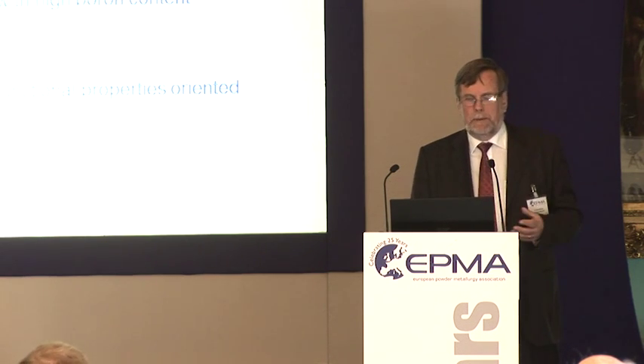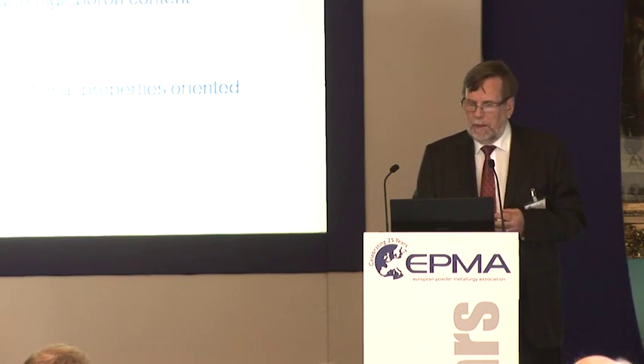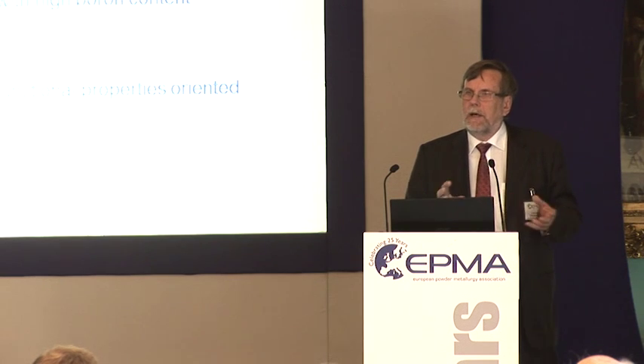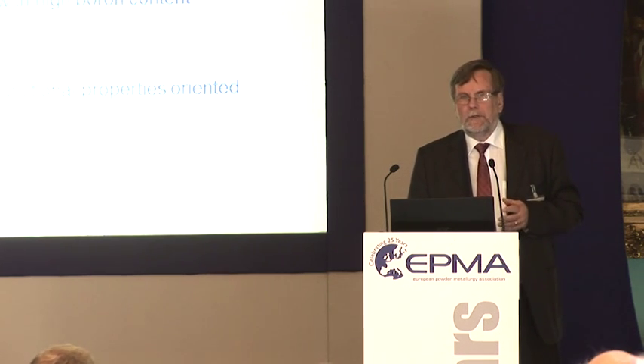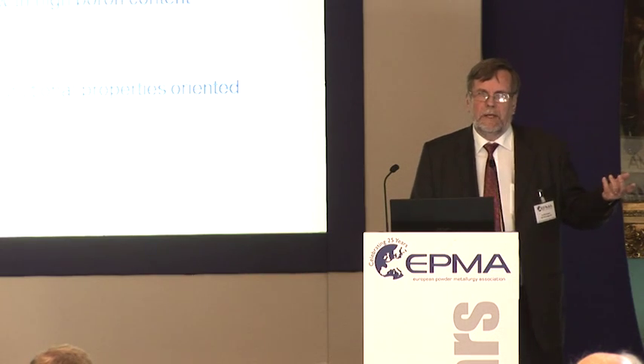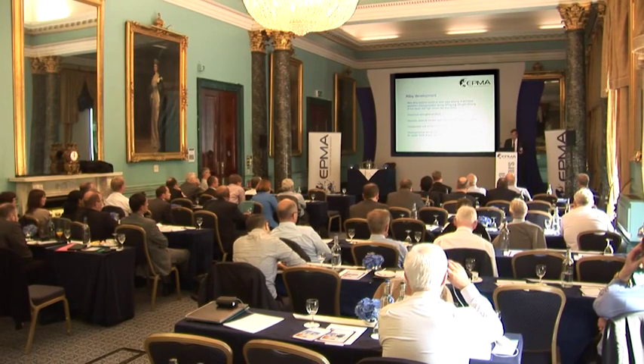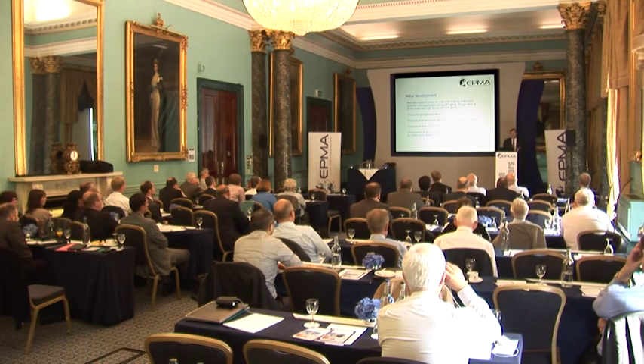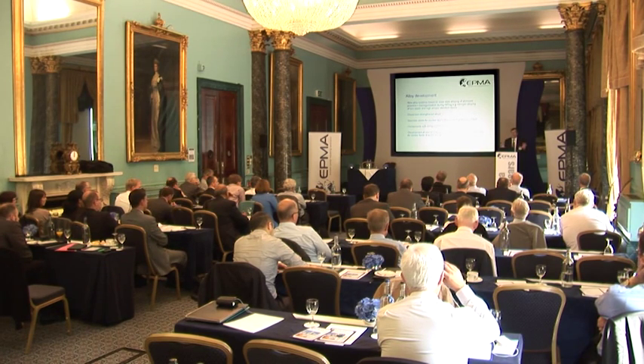Powder metallurgy over inert gas atomized powder or PREP or REP atomized powders gives numerous advantages. You can use new alloy systems based on solid state alloying. I mentioned tool steels with nitrogen alloying. You can also have interest for high alloy stainless steels. Nitrogen high alloy stainless steel is an interesting product. To take away nickel, you can add nitrogen. And the interesting thing is that when you do this solid state alloying of the powder, you get a thin layer of nitrogen on the surface, but during the HIPing process, you get a very nice homogenization through the ingot.